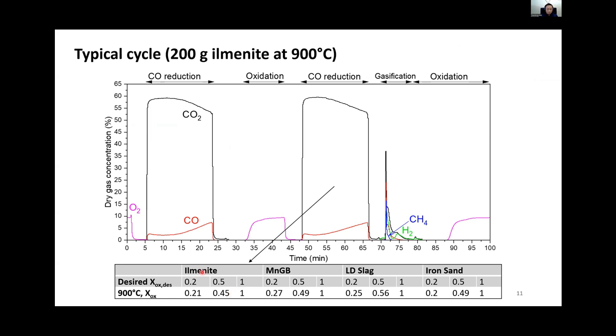And this table gives an example of the reached oxygen carrier conversion degree, which are very close to the desired value 0.2 and 0.5. The time found in the first CO reduction is then used in the second CO reduction to control the oxygen carrier conversion degree. A gasification phase starts just after this second CO reduction.